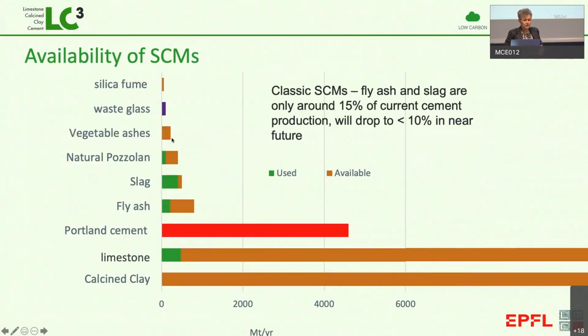And it's more or less stagnated for the simple reason that we don't have very much of these slag and fly ash. Slag, as I said, comes from producing iron in blast furnaces. Now we're recycling more and more steel. Of course, that's a good thing. But if you have more steel from recycling, you have less produced from blast furnaces. Similarly, fly ash comes from burning coal. Coal is the number one source of CO2. And many coal-fired power stations have shut down. And of course, we don't have either of these materials in Switzerland. So we do have a lot of limestone, which is the most used, but the problem is we can't go to very high levels of substitution without simply diluting the properties of the concrete.